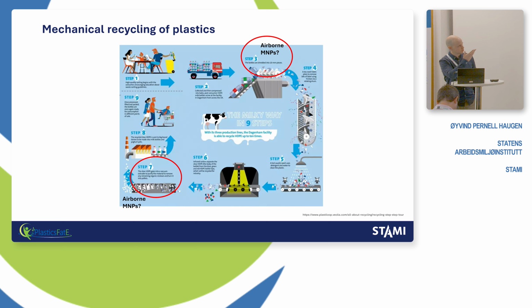So the whole process is you collect it, you fragment the plastics, you heat treat it, and then you sort it. And then in the end, it's thermally degraded and formed into these small plastic granules, which are then sold to other companies that can use them for producing new plastic bottles. And it's especially at the shredding stage of the larger bottles, and also where you thermally degrade the smaller fragments, where you potentially could have airborne micro nanoplastics arising.